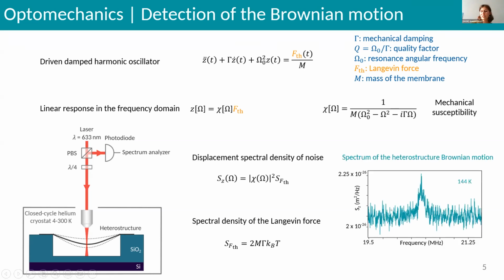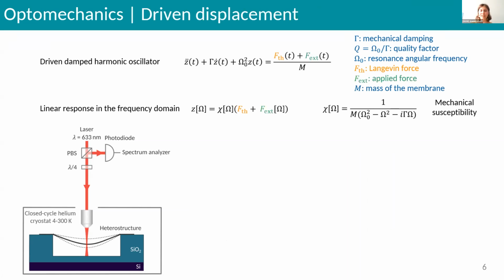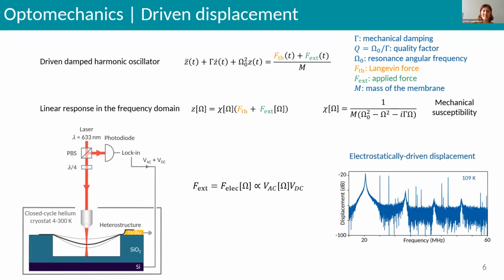So finally, we obtain such a spectrum, which contains one peak that corresponds to the fundamental mode of vibration of our membrane. So this spectrum has been taken at 144 Kelvin, and the signal is quite low and the integration time quite long, since the signal is proportional to the temperature, and we want to reach even lower temperatures to probe the phase transition. So to decrease the measurement time, we will drive the motion of our membrane. So for this, we apply an external force, and we will apply it, as I said before, using capacitive effects.